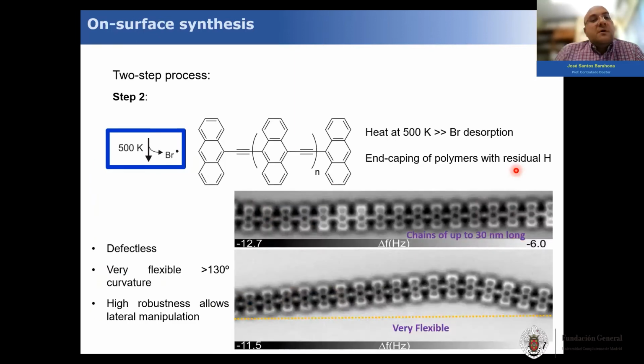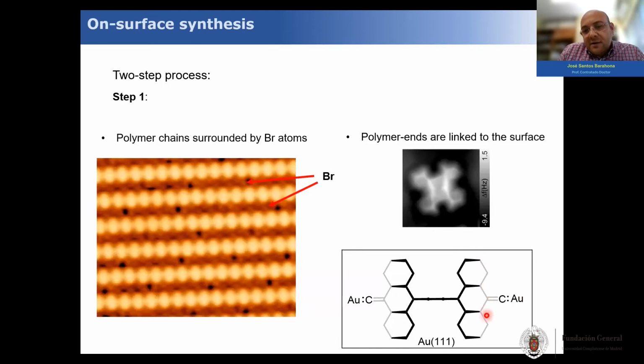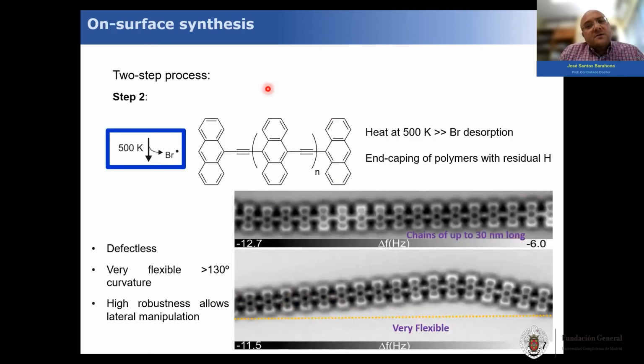In the second step of this reaction, when we heat up to 500 Kelvin, we induce the desorption of the bromine atoms, and what was previously an edge linked to the surface now detaches from the surface and is capped, or as the physicists say, becomes passivated by the residual atomic hydrogen in the chamber of the microscope. We observe very long chains up to 30 nanometers. We can even go further, I think up to 100 nanometers. They are very robust. They can bend up to 130 degrees, and when you apply a manipulation with the tip and move the chain, it doesn't break. So they are very robust.